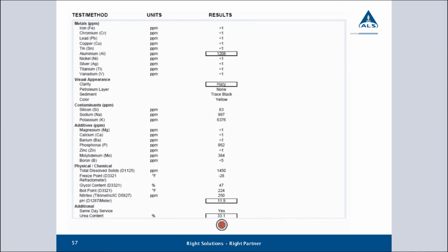Here we've got an interesting one. What we're looking at is extremely high levels of aluminium in the cooling system. The coolant has been described as hazy, so it doesn't look clear. It's got a lot of the typical additives that we would see in coolant, so it looks like a normal coolant, but the pH is very high. And something we wouldn't normally do on coolant, but because of what was suspected to be done here, they've tested this coolant for urea and found that there is urea content present.